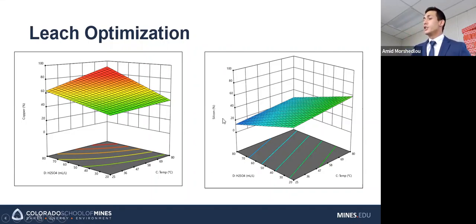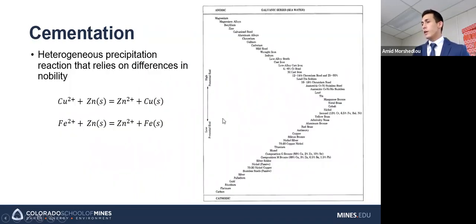And so what we can see generally is that we can sort of get a min-max, right? So right here, by minimizing silicon recovery, we still get pretty good copper recovery. So basically what we want to do is increase our acid content. And then from there, we can play around with temperature to figure out what the best break-even point is between maximizing copper recovery and minimizing silicon recovery. And we can follow this line of logic with any of the elements that we're interested in: copper, lead, zinc, what have you, right? And so from there, we can narrow down on some processing conditions that give us the best combination of recoveries for the goals that we have in mind.